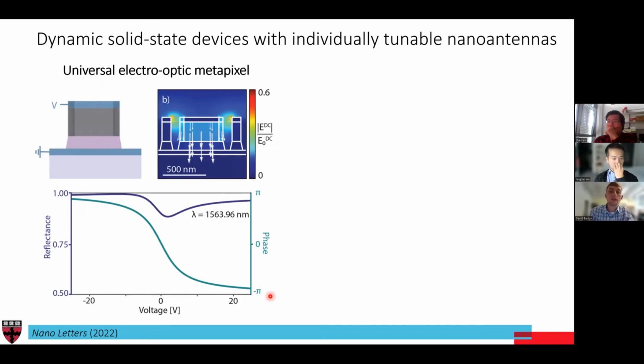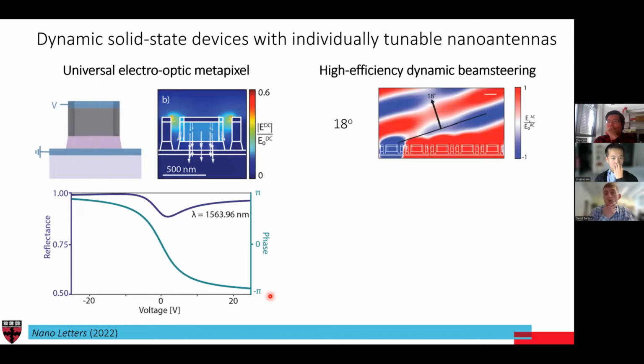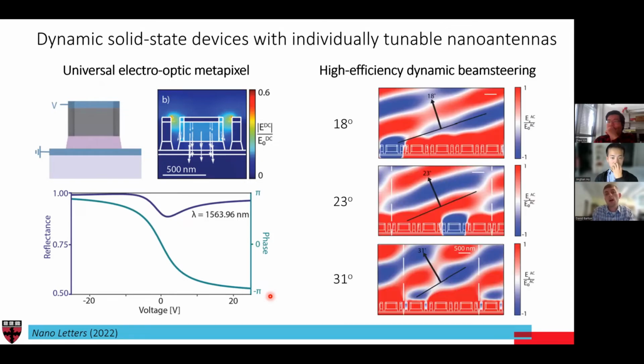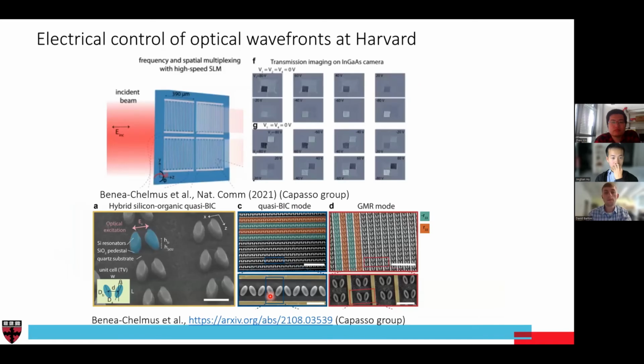which allows us basically to completely control the phase response of this material. And with this, we were able to show a variety of ways where we can dynamically change the beam steering response and make a high efficiency, very fast and dynamic beam steering element simply by changing electric fields and voltages that can be very easily controlled. And so what this allows us to do is have this very sub-wavelength, very small, compact device where we can dynamically change the optical response driven entirely by an electric field. And so we think this is a very powerful platform to designing these optical elements and making them completely reconfigurable. There's also been some other things done at Harvard.